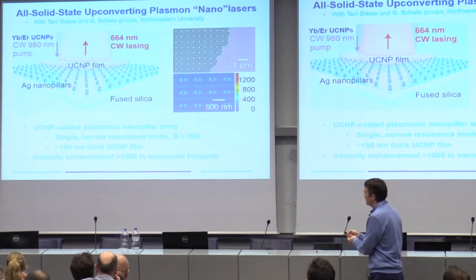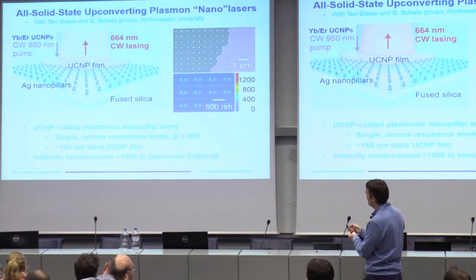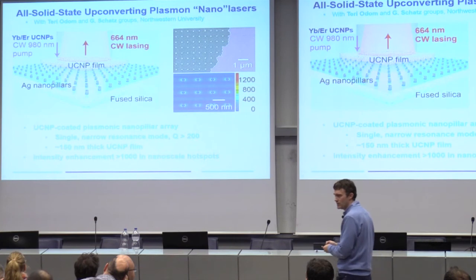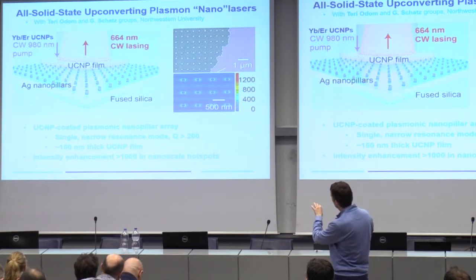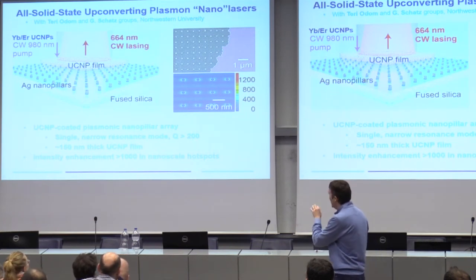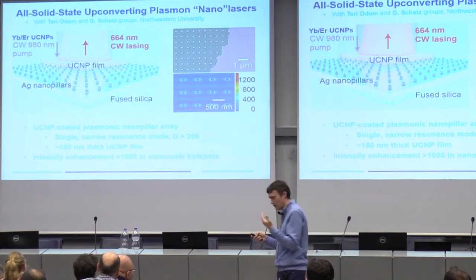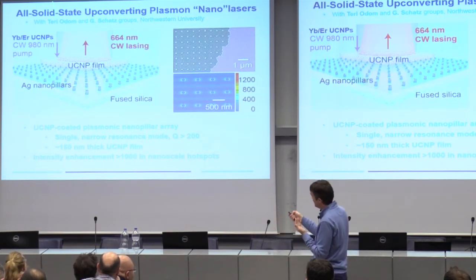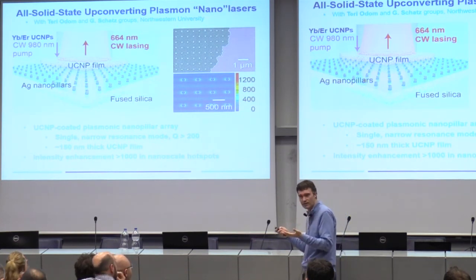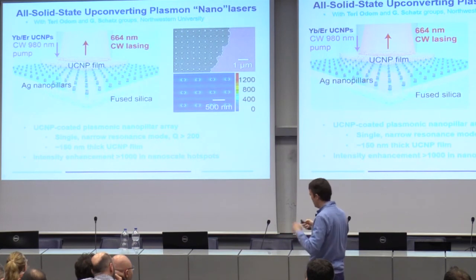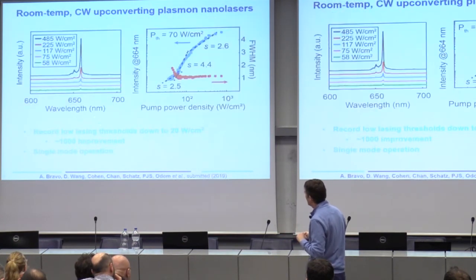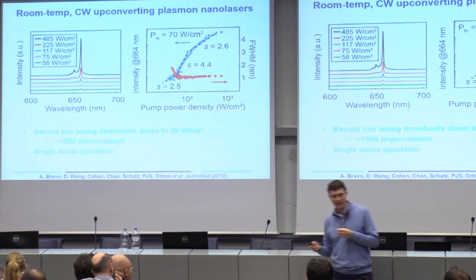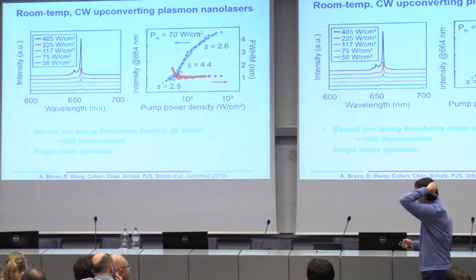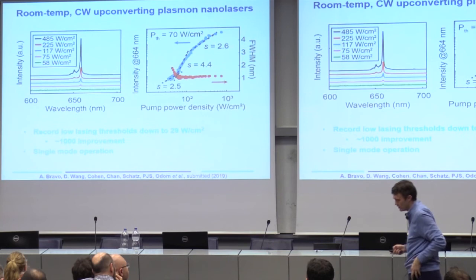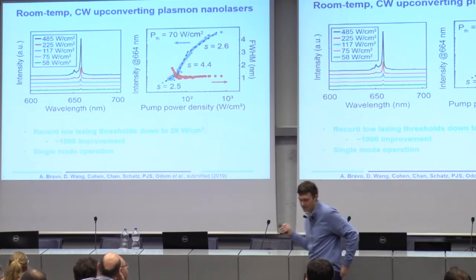So we took, again, one of these arrays. We put a thin film, about 100 to 150 nanometers thick, of upconverting nanoparticles on top of the array. Here's an SEM image. The nice thing about these arrays is that it's very easy to couple into the mode. You just design it so that you shine your excitation light normally onto the array, and it pumps the mode. And what you see is that it lases, and it lases very nicely. In this case, we were using erbium-based particles, so this is lasing in the red at 660.